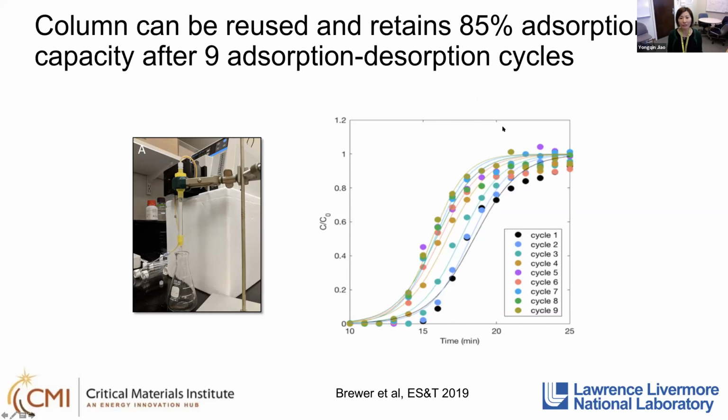The capacity of the beads varies based on the feedstock and slightly based on the conditions we tested, but I would say that it's about 10 to 15 milligrams per gram of absorbent that we normally see. And during manuscript review, submission and publication, we got some comments from the reviewers about the relatively low absorption capacity compared to other absorbents such as the granulated activated carbon, the GAC column.